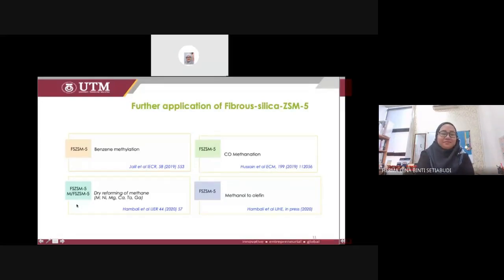And then when we modified the fibrous silica ZSM5 with metals, which are nickel, magnesium, calcium, tantalum, and also gallium, we found that the tantalum gave the best result on the dry reforming of methane. And then we also tried the metal-free fibrous silica ZSM5 on methanol to olefin. So what I can say is that this is some of our successful results on the modification from the KCC1 to the fibrous silica ZSM5. This is some successful story from us.